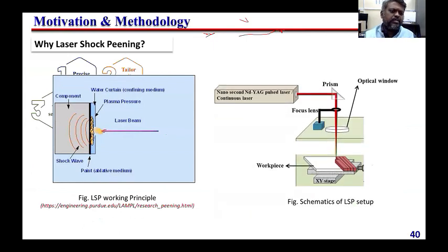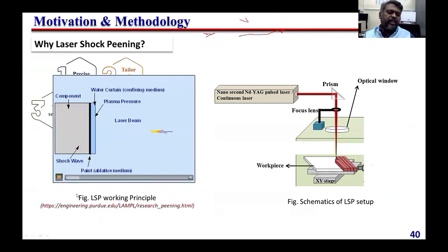So what is the basic phenomenon that will happen? Suppose the laser beam is bombarded over your particular sample, so that will give some kind of high energy plasma. When it is hitting or bombarded with this material, it will convert into a very high energy shock wave, which will be induced into the particular material. Because of that, it may refine the material, or it can change, any phase transformation may also happen. Mostly it will induce a microstructural refinement. So that is the main idea of doing laser shock peening.